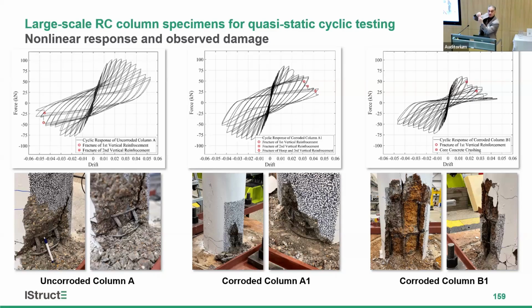Because of the buckling, we get stress localization, and the bars fracture even quicker. And this one is the well-confined column after the corrosion, which essentially had minor buckling and was mainly governed by flexure failure. And this is the lightly confined concrete, and you see it is governed by the compression failure. And we can see it in the response.